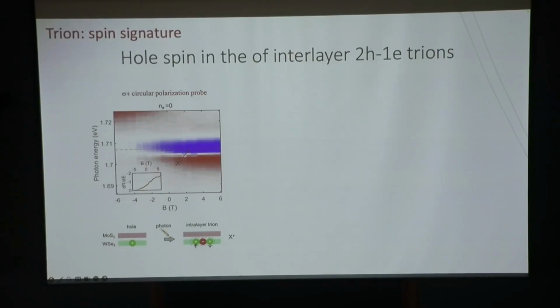First, let's see what happens when you have just free holes. A free hole will have a paramagnetic spin. So if you apply a magnetic field, the spin polarization will change, and the spin-up density of the holes will vary continuously. This is what I talked about before. By using circular polarization, you can see there are more spin-up holes with positive magnetic field, and fewer spin-up holes with negative magnetic field.